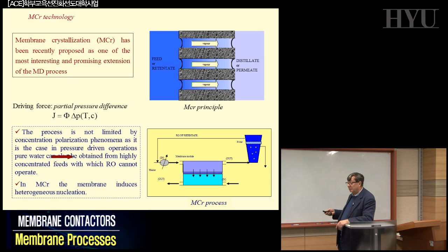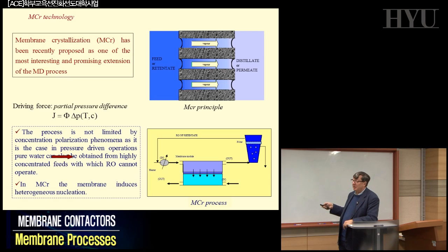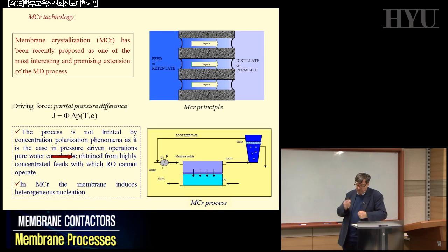And this is, again, becoming quite interesting because initially it seemed that this system is only to evaporate. It helps you to evaporate. That is typical crystallization by evaporation. We arrive at saturation and you precipitate your crystals. It's much more than this. Because when you start to do this, you learn that the properties of your polymers, the morphology of the surface, the surface energy, etc., induce a lot of phenomena. For example, reducing the activation energy of the nucleation. So the crystal can grow much faster than normal.